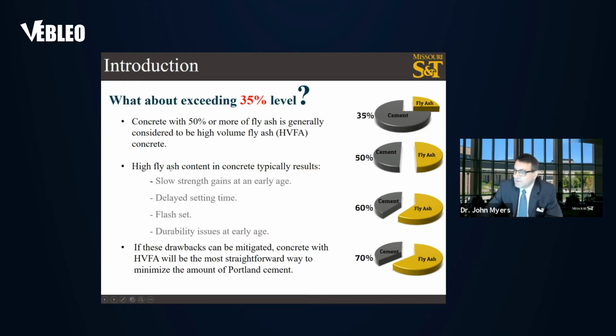As you can see here, there's a few concerns, I guess you could say, with high fly ash usage. This includes slower strength gain of the concrete, delayed setting time, flash set, and potentially the durability at early ages. But if these drawbacks can be mitigated, concrete with high volume fly ash will be the most straightforward way to minimize the amount of Portland cement.